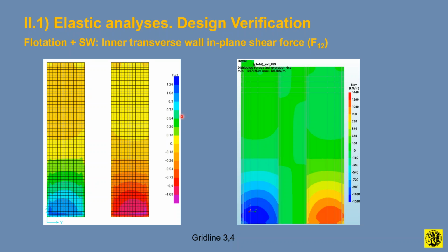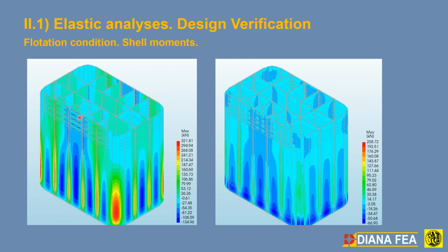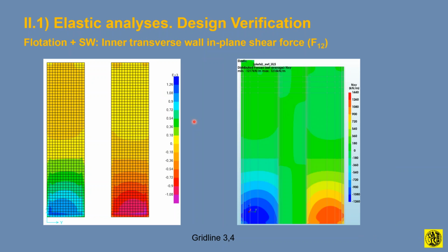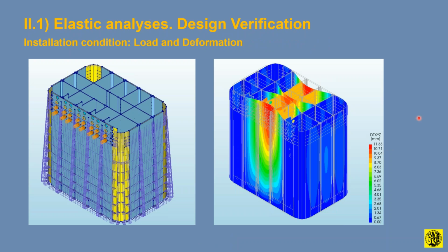We can see, like the flotation case, this is the typical grid line 3 and 4, which is this one here, the two walls across with the chamber in between. So the F12, the shear forces, which are developed because of the bending action of these shear walls as they cave inwards, supported by the longitudinal walls, are shown here using the two programs, comparable. And now we go to the installation condition, whereby the full sea level is imposed and then the remaining is 8 meters below inside, the most critical case.